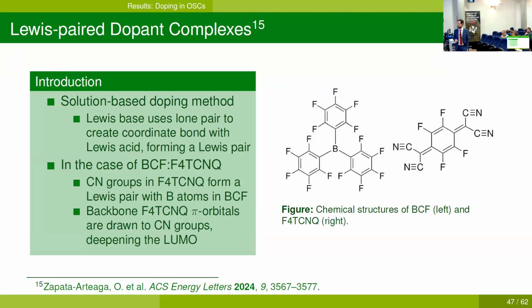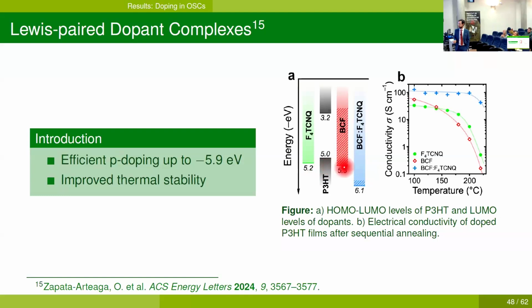When this happens, the cyano groups then become electron deficient. Therefore, the pi orbitals from the backbone of F4TCNQ are attracted to the cyano groups, which in turn leaves the backbone electron deficient, which deepens the LUMO. And if we recall p-doping from the previous slides, deepening the LUMO means that now we are able to efficiently p-dope up to much lower values of HOMO, of any organic semiconductors.